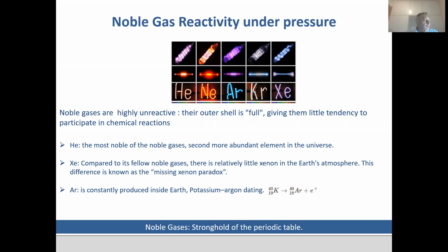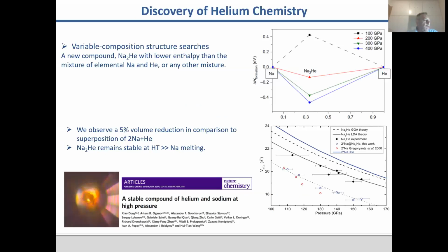Now, there are compounds with helium and other noble gases such as van der Waals compounds, but in this case, the idea was whether we can form stable compounds with real bonding. And according to theoretical predictions, at about 110 to 120 GPa, there is a compound between helium and sodium, the sodium helide, if you like, that becomes stable. And in this case, the theory predicted a real bonding between these two elements.